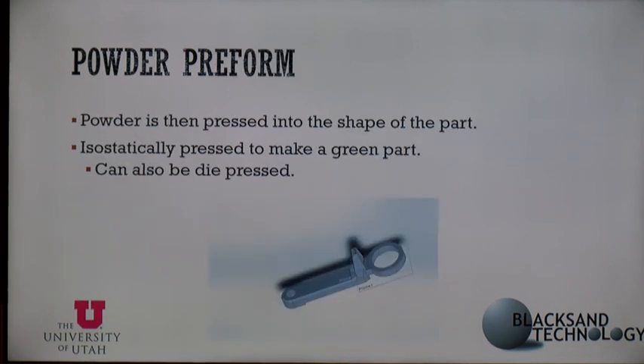Now, when we get into preforms, that's how we create these parts. There are a few different methods, but generally all of them have to be pressed into the shape of a part that's oversized, because during sintering you shrink. You're going to shrink a certain amount, let's say 15%. So you need to make a part that's 15% larger in all dimensions, and then it'll eventually shrink to approximately the same size, and then you can machine down from that. You can either isostatically press it under high pressure with fluids, or you can die press it. With die pressing, obviously the cost of the die would cost more money, but I have methods for both right here in front of me. So that's the essential idea.